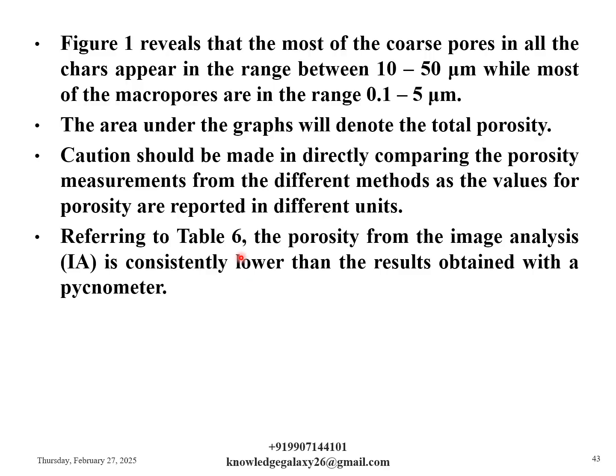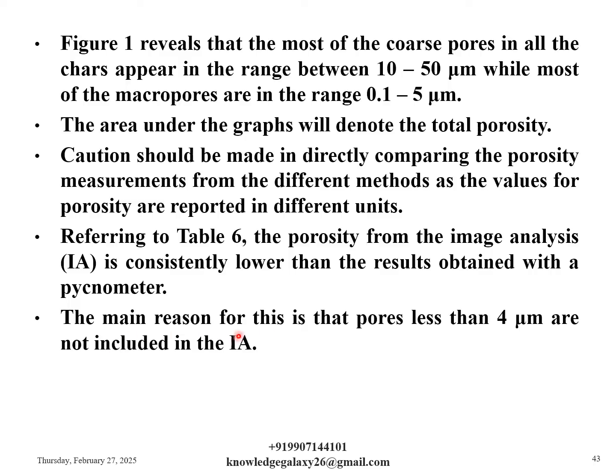Referring to table 6, the porosity from the image analysis, that is IA, is consistently lower than the results obtained with a pycnometer. The main reason for this is that pores less than 4 micrometer are not included in the IA, that is image analysis.